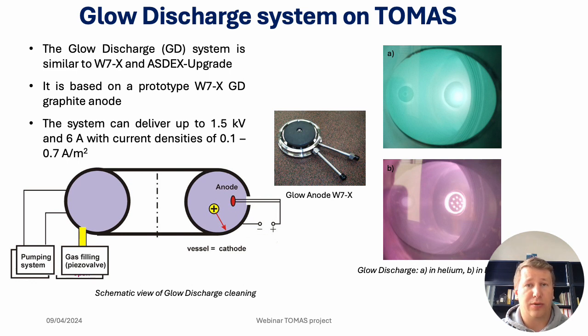The glow discharge anode of TOMAS is the same as the anode for large fusion devices such as Wendelstein 7-X and ASDEX Upgrade. It allows for easier extrapolation of glow discharge optimization results. The optimization is done by increasing the impurity removal rates through the variation of glow discharge parameters such as working gas pressure and anode current. We also have to take into account the adverse effects of glow discharge in the optimization of this procedure.